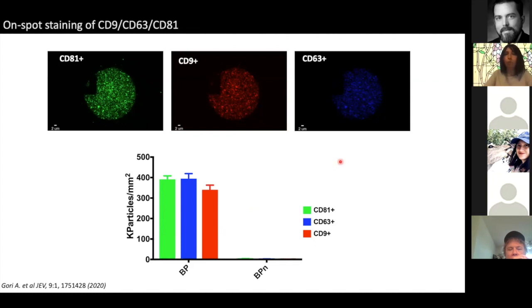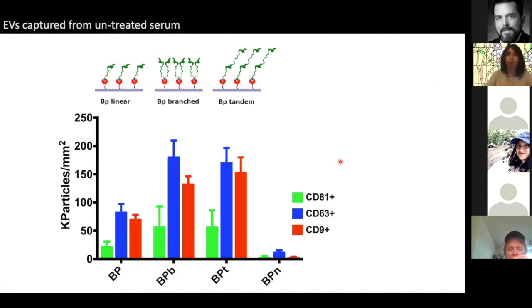And then we moved to challenge our chip with a really complex sample. We used untreated serum. So basically, we just diluted serum 1 to 10, and we filtered it by a 0.2 micron filter, and we incubated this on the surface of the chips.